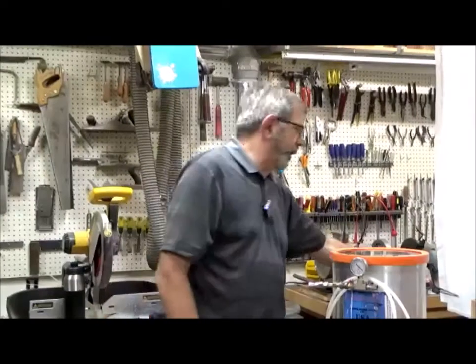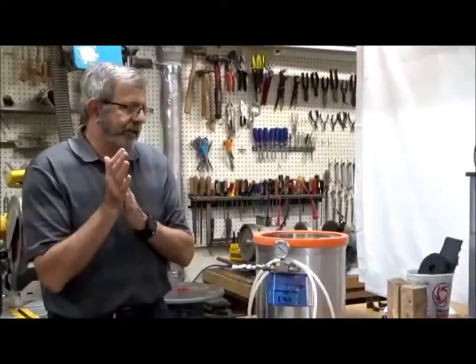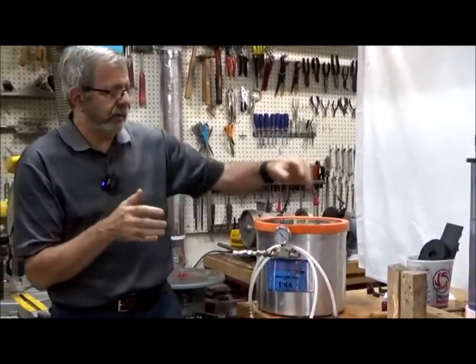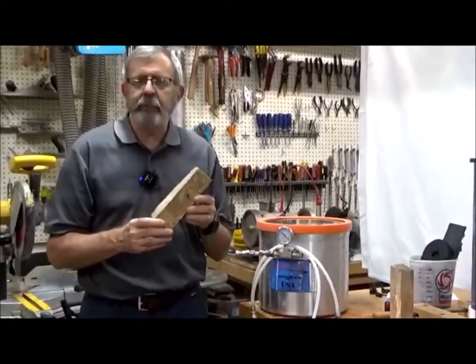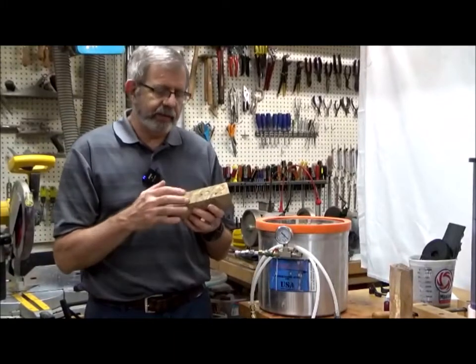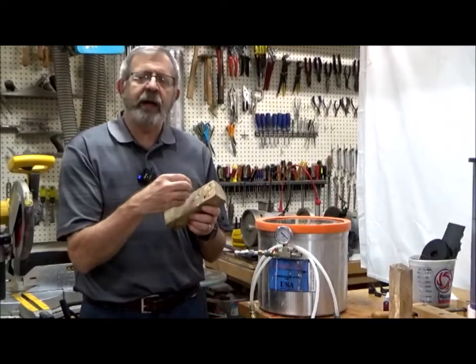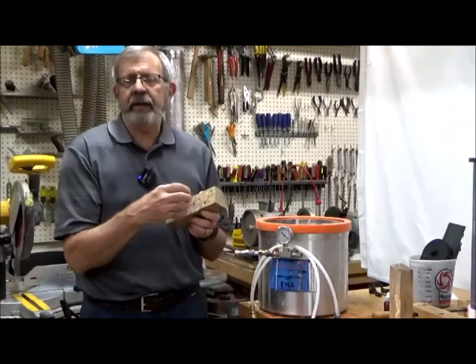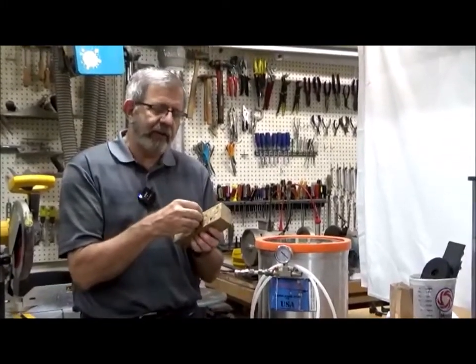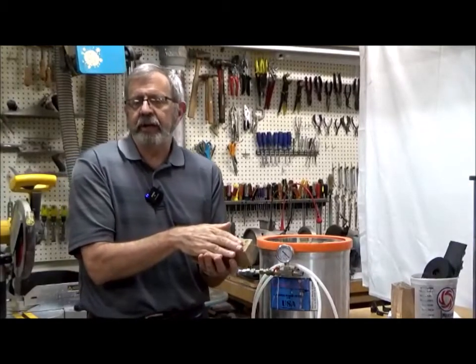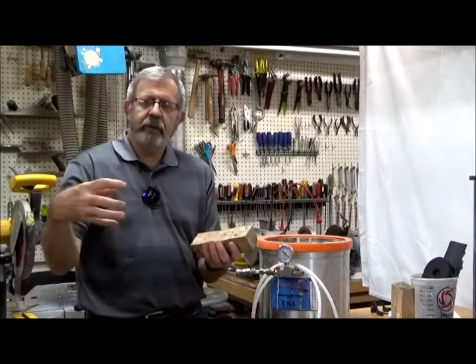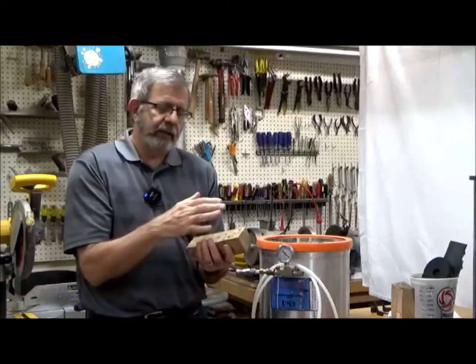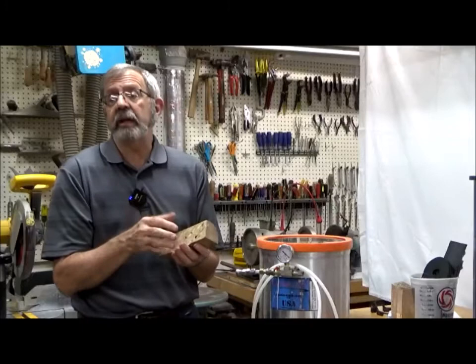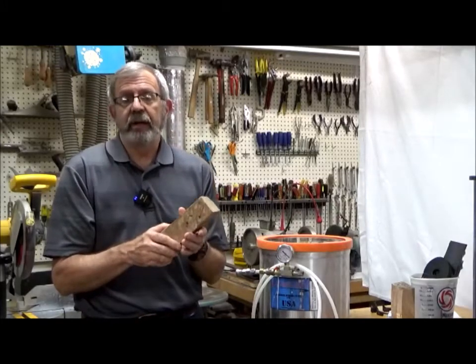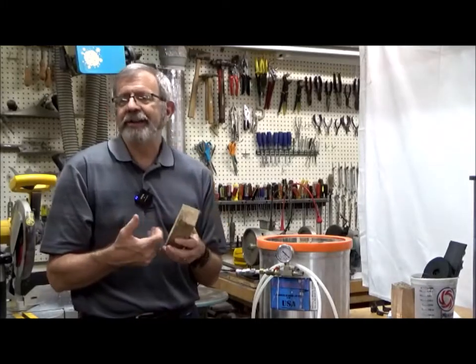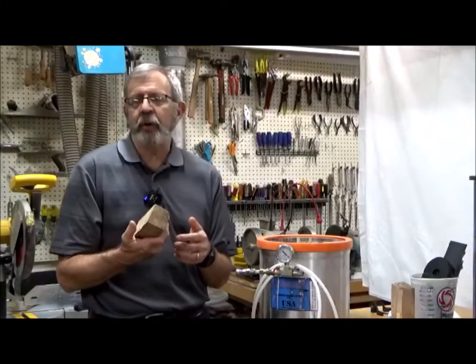So what is resin stabilization, vacuum stabilization? It's a process where you create a vacuum, you put a substrate, and this is a piece of really punky burl, under vacuum that draws the air out of the pores of the wood and causes them to be under negative pressure. And once you get the air out of the pores, it's like a sponge. It's submerged in a liquid. And when you release the vacuum, the resin gets sucked into the pores of the wood. And that resin stays liquid until you bake it. And with cactus juice, it's at 200 degrees. And the resulting product is a very hard, durable finish that allows you to use some otherwise unusable wood.